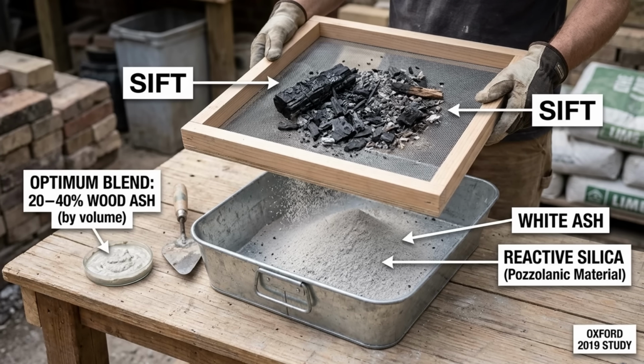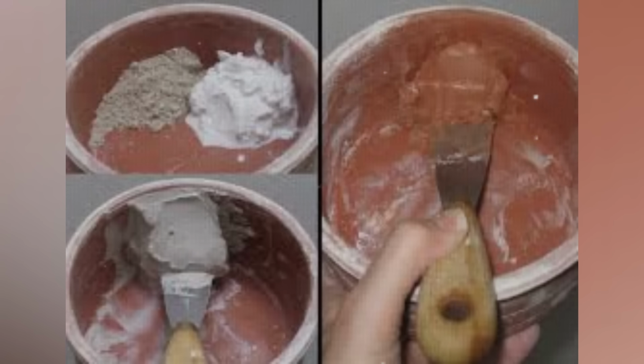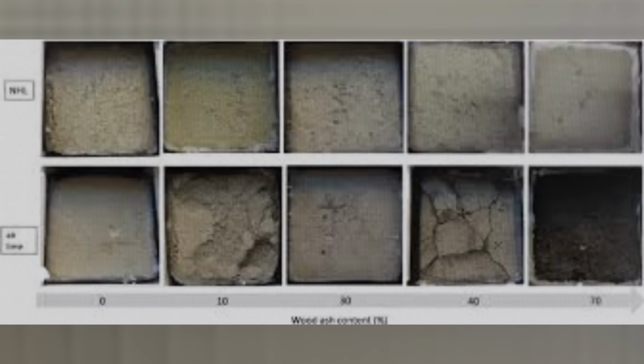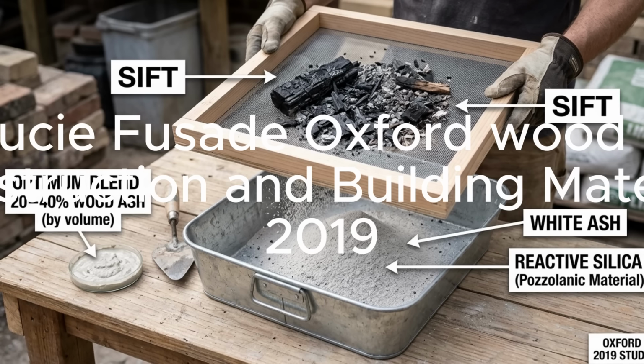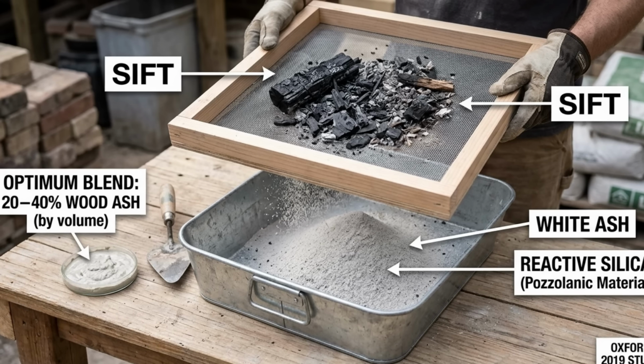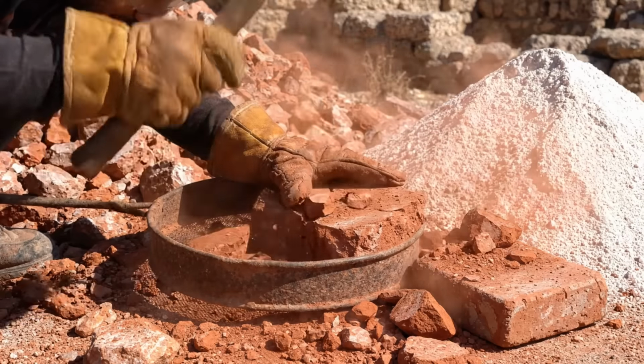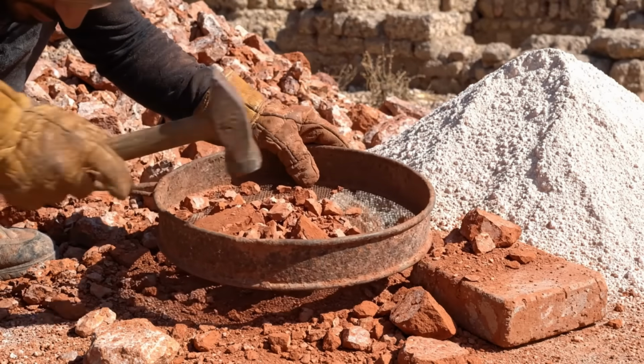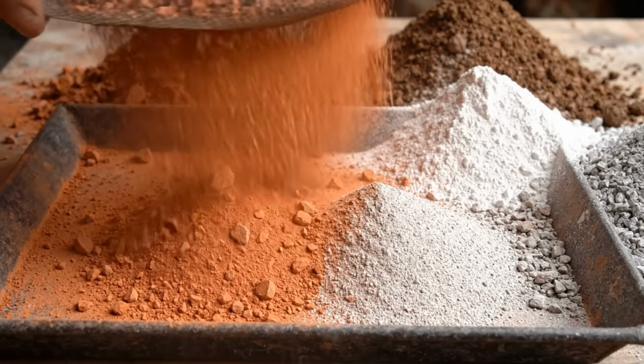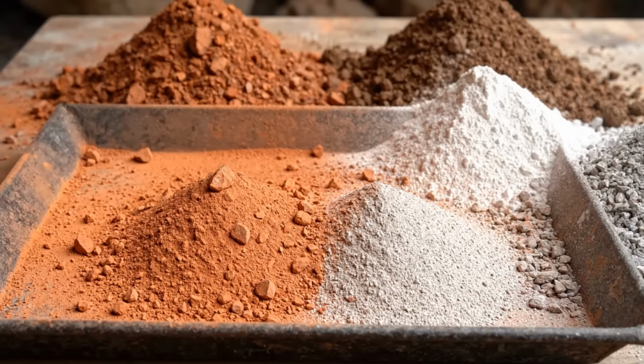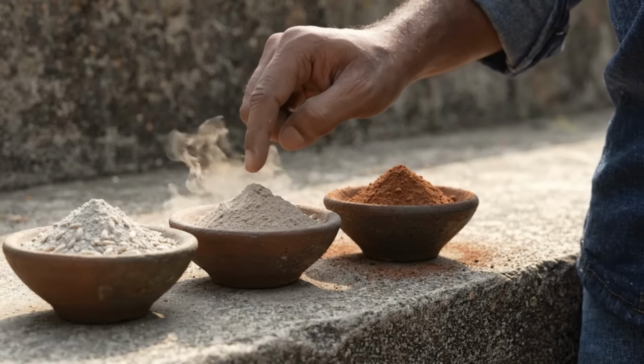Step 2. The Pozzolan. If you have a wood stove or brush fire pit, sift cooled ash through a window screen to remove charcoal. The whiter the residual ash, the better. Complete combustion produces the most reactive silica. A 2019 University of Oxford study by Lucie Fusade and colleagues, published in Construction and Building Materials, identified 20 to 40% wood ash as the optimum pozzolan content for lime mortar in damp environments. Wood ash genuinely behaves as a pozzolan, despite being below the formal silica content threshold, because its fine particle size dramatically increases reaction surface area. No wood ash? The Theodosian fallback works perfectly. Crush fired clay bricks from any demolition site and screen the dust to the same fineness. Rice husk ash and sugarcane bagasse ash also qualify if combustion was complete.